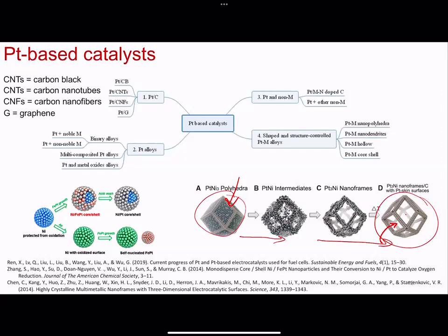In order to keep all these nanostructures apart and prevent agglomeration, there are hydrocarbon ligands that you don't see in the schematic, like C18 chains. The next particle will have these, and that will prevent them from agglomerating. But obviously that will prevent the catalyst from performing, because now the surfaces are not exposed. So what you do is deposit, sonicate, throw it in some carbon powder and just sonicate the heck out of it.